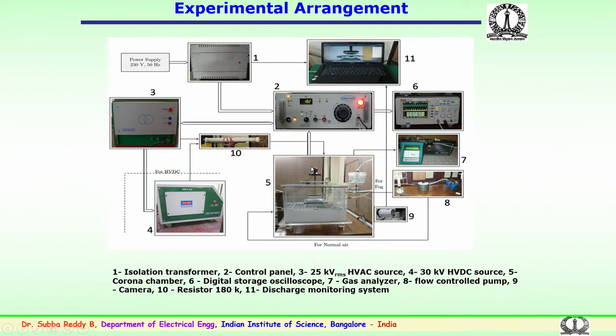The sample is kept here, the high voltage is connected and continuously monitored over a period of tens of hours or 100 hours, and the performance of this sample is checked for AC or DC. We have a facility for this chamber where we can inject natural air, or a fog, or an acidic fog, and the effect on the samples can be studied. So, this is a specially made chamber, and the corona activity is monitored in the monitoring system, and the leakage current is measured using a digital storage oscilloscope.